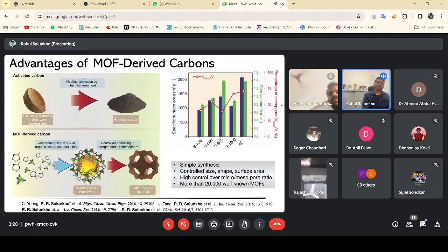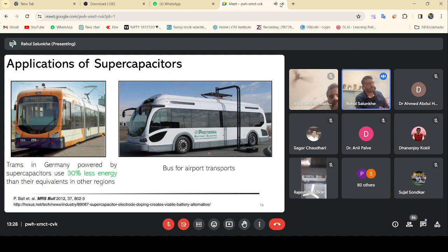So we can improve the performance of the supercapacitor by using this MOF if we have a very narrow pore size distribution in the micropore region and a wide pore distribution in the mesoporous region. This kind of pore structure can be used for various supercapacitor applications, and because of that we can improve the supercapacitor performance. And if we can improve it, we can use it in many different applications, such as trams in Germany. They are powered by supercapacitors, which use 30% less energy than the equivalents in other regions.